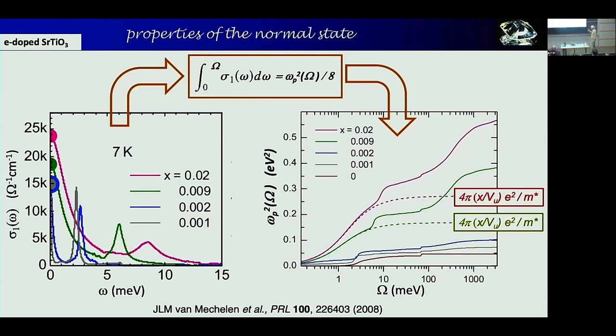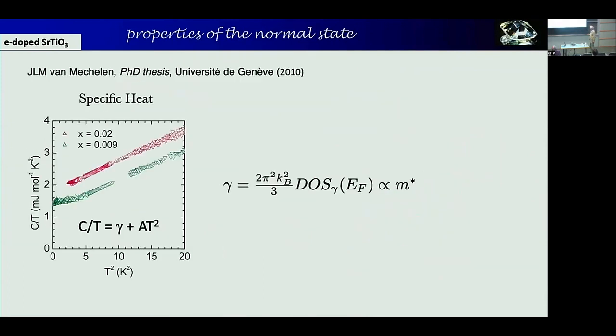For two dopings, I'm going to use that information in the following plot. But before I show that, I first show the specific heat. That's another way to do it. If you make a plot of C over T versus T squared, then the intercept extrapolated to zero temperature gives you something that's proportional to the density of states at the Fermi energy, and the density of states has a very simple relation to an effective mass.